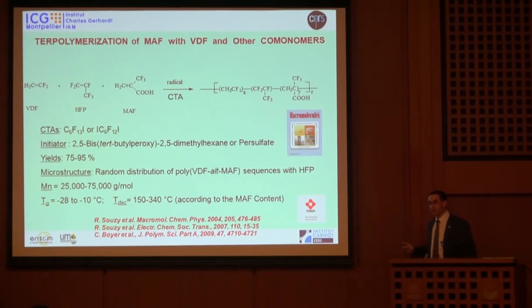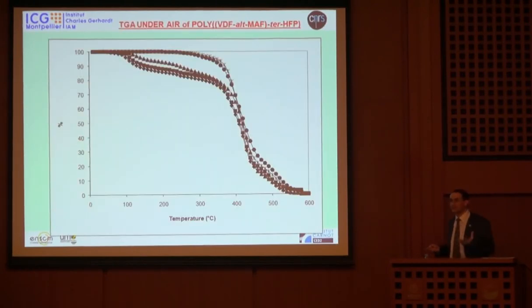So I found this structure very, very interesting. And we said, okay, this can be an interesting approach. Molecular weights were ranging between 25,000 and 75,000. The Tg increases when you increase the content of MAF, which is very interesting, but when you increase the content of MAF, the thermostability is decreasing. And indeed, we see that we have a lot of decarboxylation.